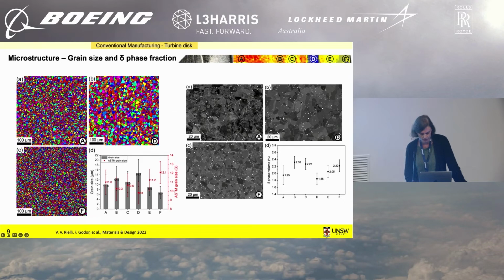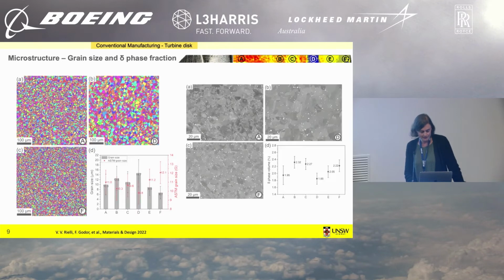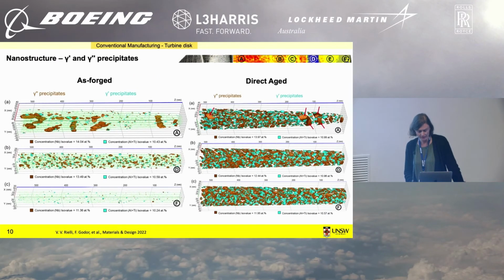Another example is shown here. So what we're interested in is having a slightly higher volume fraction of these white particles than we can see here in this region D. That's the so-called delta phase. It's very important to pin grain boundaries during processing, and it's also an important source for niobium that we need in the next step.